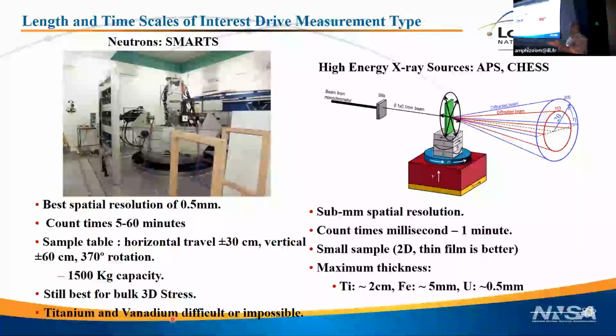I was talking with somebody before the talk about the convert fuels, the program to convert highly enriched uranium to low enriched uranium in research reactors. Those are essentially two-dimensional foils of uranium molybdenum. The X-ray beam is really great for measuring stress in that because you can make assumptions about the out-of-plane stress field. That's where the synchrotron beam, in my mind, really shines for stress measurements.